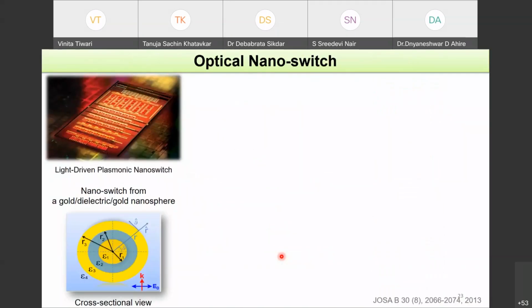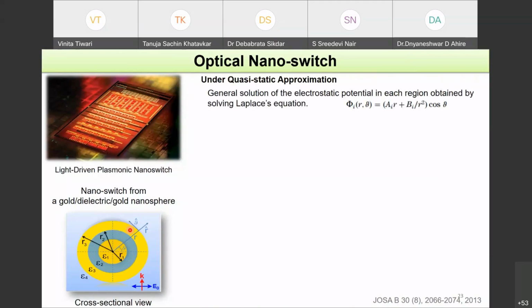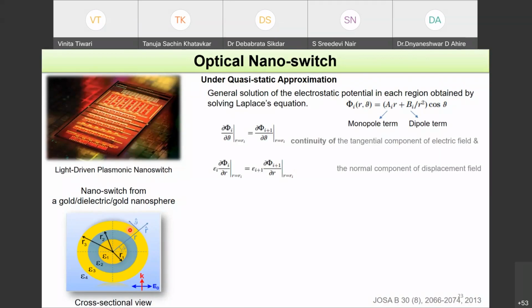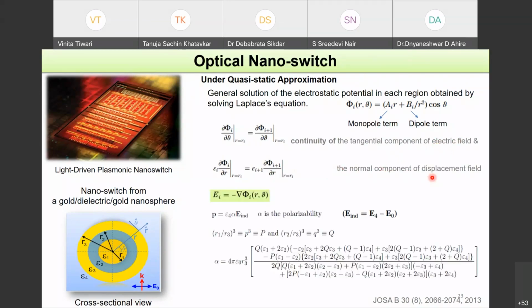So let me take you to one example of optical nano switch, how you can design an optical nano switch based on plasmonics. So let us consider one nanoparticle, which is basically a gold dielectric gold nanosphere. So it's a 3-layer system. And again, you can use quasi-static approximation to solve for electric potential in each region. And there you can apply continuity of the tangential component of electric field and the normal component of the displacement field at each layer, and that will give you the polarizability